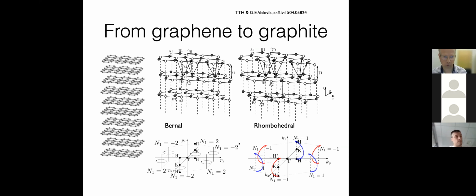I will not talk too much about Bernal graphite, but actually about rhombohedral graphite, which has a flat band on top and bottom surfaces. But let's say if you want to make a model of this, the easiest way is to look at what happens if you have just Dirac points, several Dirac points, and then you start stacking them by coupling pairs of atoms. You make the rule where you always couple one blue atom to one red atom, so 1A to 1B atom in the sublattice in one way or another,